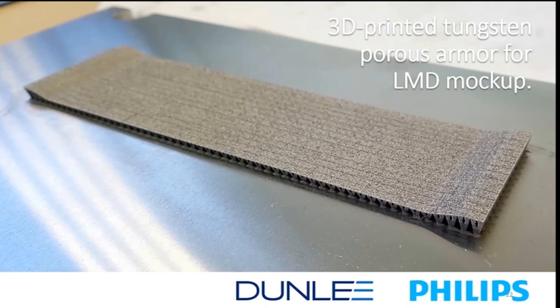There is one challenge with printing, though, a very technical, practical challenge, which is that currently these printers work with a powder bed. There is a flat bed of powder, and you pull the laser across that, and then you swipe over a fresh layer of powder. But this bed has to be perfectly flat. But the diverter pipes may not be perfectly flat, and in fact, because they are in assembly, maybe the tolerances are just not good enough.